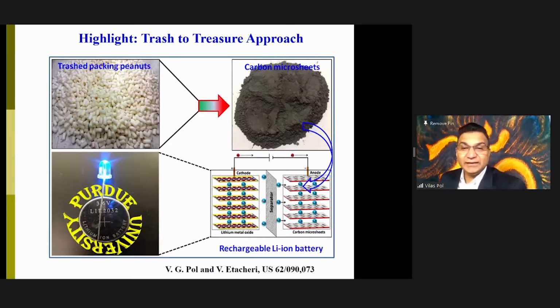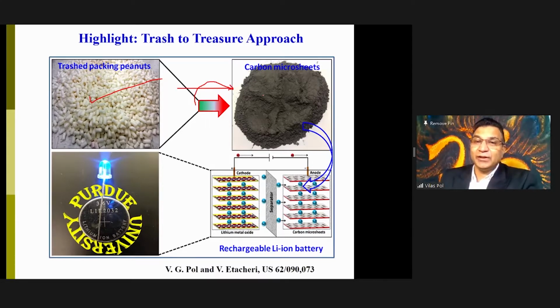So one of the technologies I was telling you that we developed, we call it the trash to treasure approach. Really, we took a material that is useless, that you're throwing out, it is a burden on the earth, it can stay up to a few hundred years. If it is polystyrene based, it doesn't want to decompose, it can just stay there. So we developed a process that could convert, in a short time, these trashed packing peanuts to this dark black powder that is graphite, or a carbon powder, that can act as a negative electrode for your battery, and it can reversibly store the energy, namely it can charge and discharge.